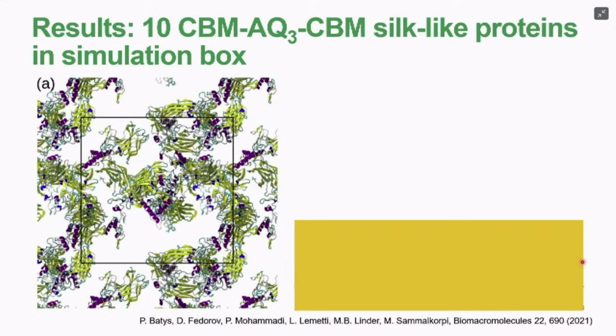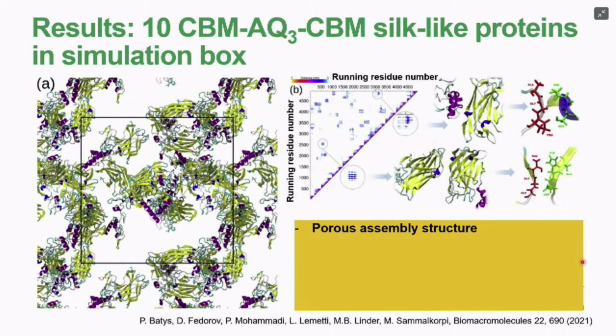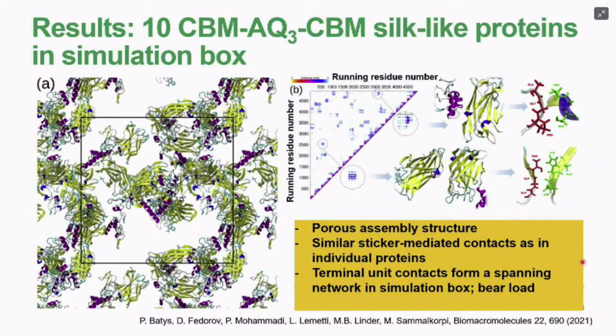Then putting 10 of these in one simulation box. So this is a much bigger simulation. The box is around 16 nanometers now. What we are getting out is a porous assembly structure. And in the same way as before, we can analyze what kind of contacts there are. The contacts are pretty identical to the single protein case, but now between the different proteins in the solution. So we get similar sticker-mediated contacts as for individual proteins. We get terminal unit contacts that form a spanning network in the simulation box, and those are bearing load. And as I already said, this is quite incomplete relaxation, so we needed to run lots of these simulations, starting from different configurations, starting from different protein structures that are being put in.